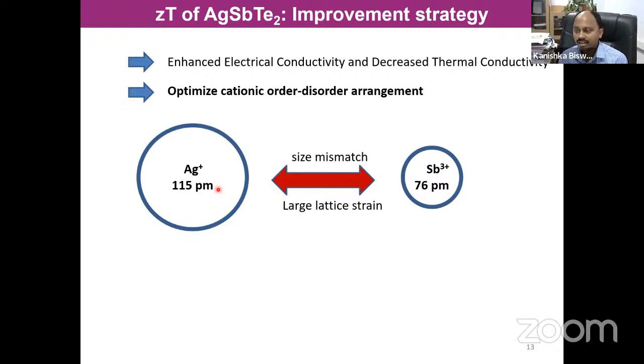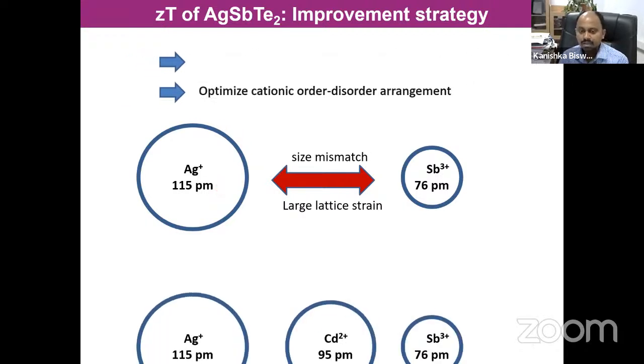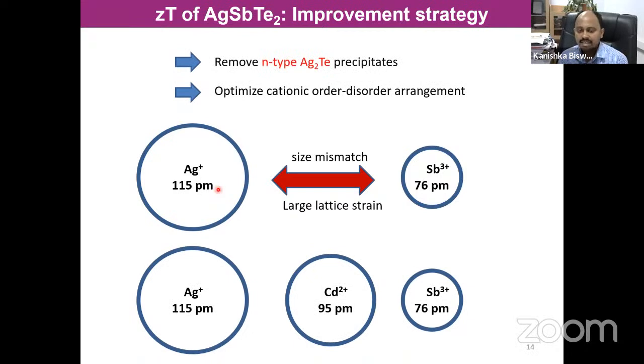So how do we make them ordered? We tried to dope the antimony and silver sites with many ions throughout the periodic table, and we ended up with cadmium. Cadmium has exactly the average charge, +2, of silver and antimony, and exactly the average size. If you add 115 plus 76 divided by 2, it is equal to 95. As soon as we dope cadmium, silver and antimony get partially ordered in this compound, and we have several proofs of that. I'll give the proof now.